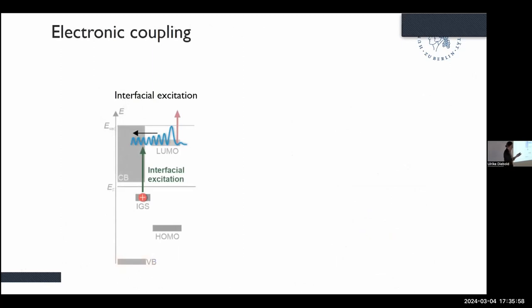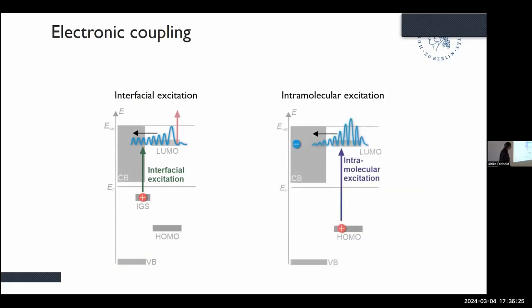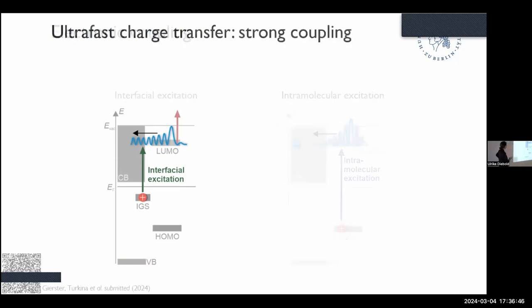Now, in order to get an answer for the charge separation issue, we perform two different experiments. One is the interfacial excitation, where we use this in-gap state as the initial state for the photoexcitation, then we resonantly excite into the LUMO of the 5P pyridine molecule. So this excitation in itself is already a charge transfer. We kind of charge the molecule. And then the second experiment is the intramolecular excitation. That's the usual resonant excitation of the molecule, where we determine the photon energy that we use with UV-vis spectroscopy. So I will show you both results in a moment.